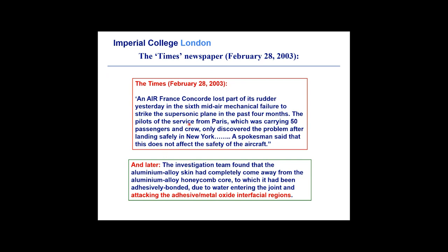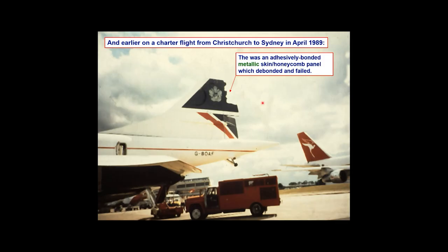But in 2003, you can see it lost part of its rudder halfway across the Atlantic. The plane landed safely. A spokesman said that it doesn't affect the safety of the aircraft, which is very true, of course. The investigation team found that the aluminium alloy skin had completely come away from the honeycomb. Remember that early honeycomb I showed, where you have a honeycomb core and a skin that's glued, and the two had completely come away. They found this was due to water entering the joint and attacking the adhesive metal oxide interfacial regions.